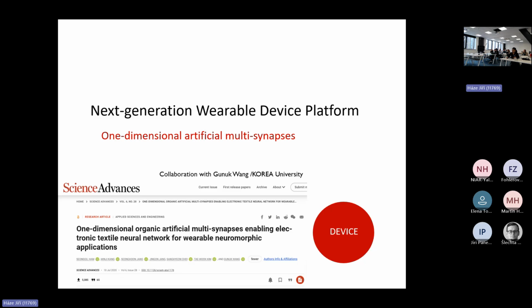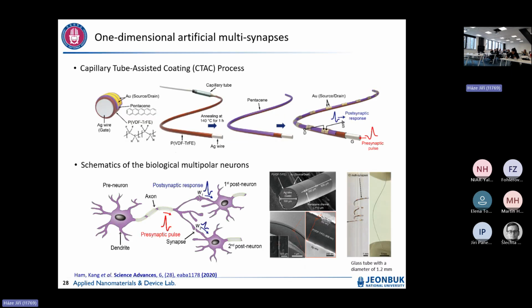Then from this work, we are trying to make a neuromorphic fiber. So the device structure is very similar, but we just change the contact on the fiber. So here, this is a conventional ferroelectric fiber. We use the CTAC process. Then we can carefully coat the PVDF-TrFE here, right before the deposition of the pentacene. So unfortunately, the pentacene was deposited by thermal evaporator. Then we deposit gold electrodes for source and drain.